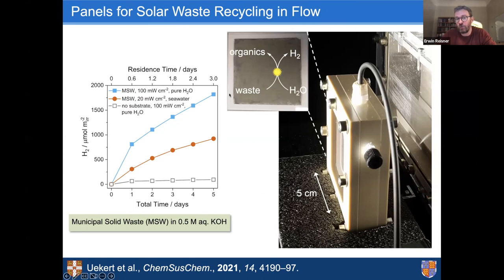And now we don't have a suspension in the photoreactor. We actually deposit the photocatalysts on solid substrates or glass. And you can really make the glass window of your photoreactor a window with co-deposited photocatalysts. So in this case, we flush in the degraded or depolymerized substrate. And when it touches the window, it gets broken down into organics that you can flush out. And in the headspace, you form the hydrogen. And also here we see the hydrogen versus time.